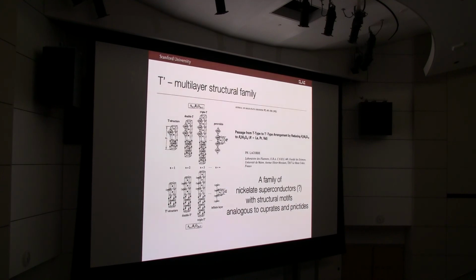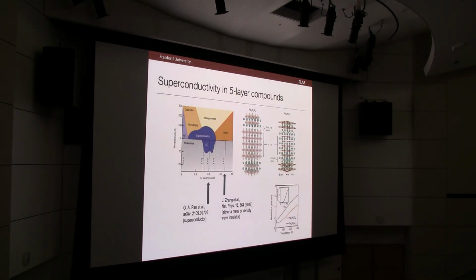And one could imagine that there might be the possibility of an extended family of superconductors along the structural motifs of the cuprates, the pnictides, and many systems that we know and love. And very recently, the first steps indicating that's the case have been reported online. So this is a reproduction of a cuprate phase diagram. The interesting point of this layered, in this case, 5-layer structure, is that this spacing layer is essentially doping this guy, such that the average hole doping level is 1 over n, where here n is equal to 5.